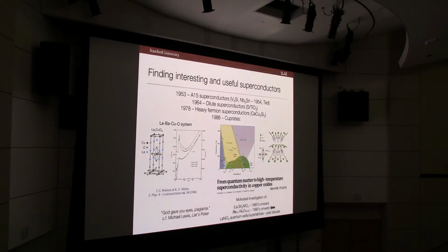In fact, it manifests these electronic correlations that are poorly screened in the fact that if you look at the so-called parent compound, lanthanum 2 copper O4, if you thought about the electronic structure in the conventional ways, you would conclude that this was a metal, a half-filled band. But what it turns out is that the electron-electron interactions are so strong that rather than a metal, the electron kinetic degrees of freedom are frozen and charges localized on each site, such that all that's left is the spin degree of freedom and the ground state is an antiferromagnetic insulator.